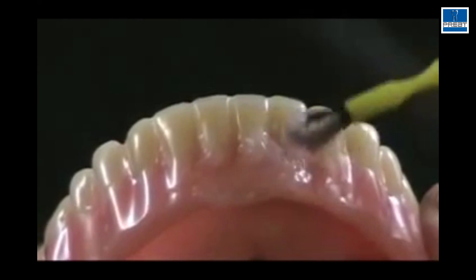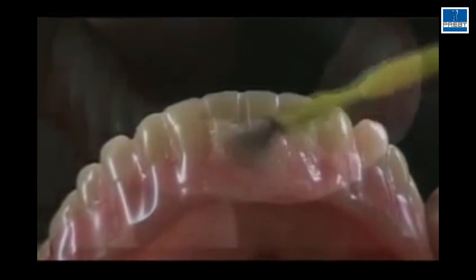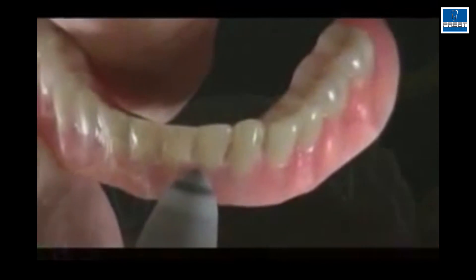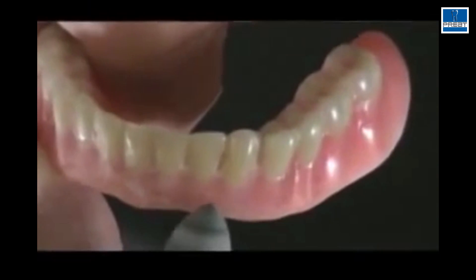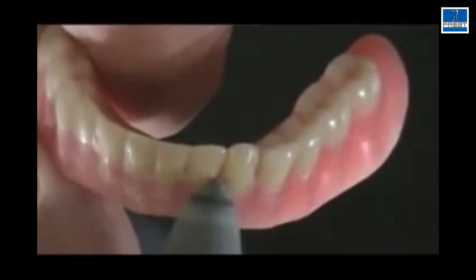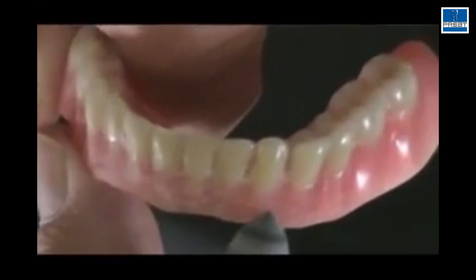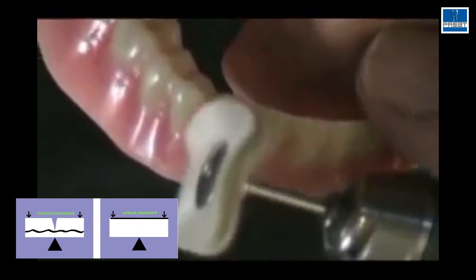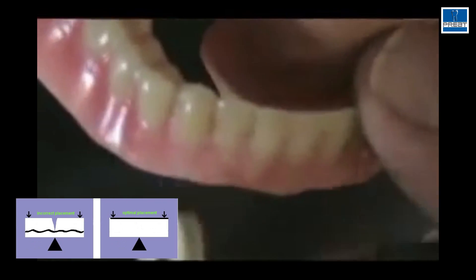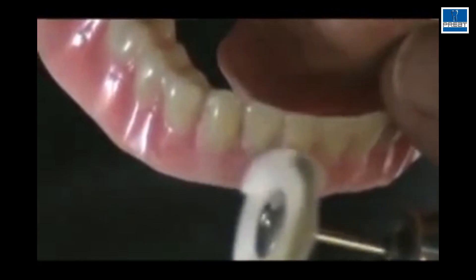How strong is a repair system like this? When we ran the tests with Permamesh originally, we were talking to the students doing the testing at the PROS Residency. We tried to get them to put the mesh at the edge in the tension-compression areas, but they put it in the middle of the block of acrylic because it was easier to process. And even then, they found it was 100 times stronger than unreinforced acrylic.